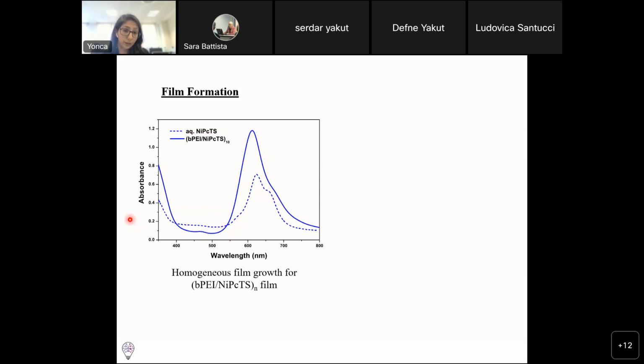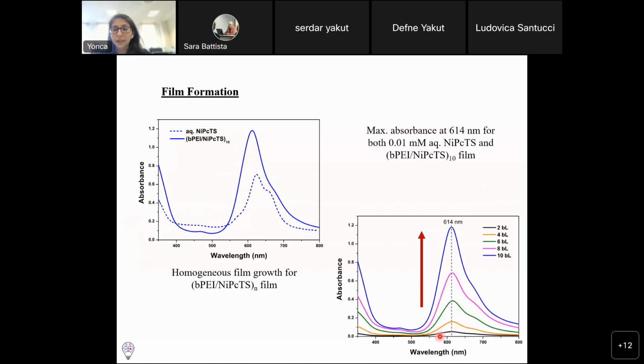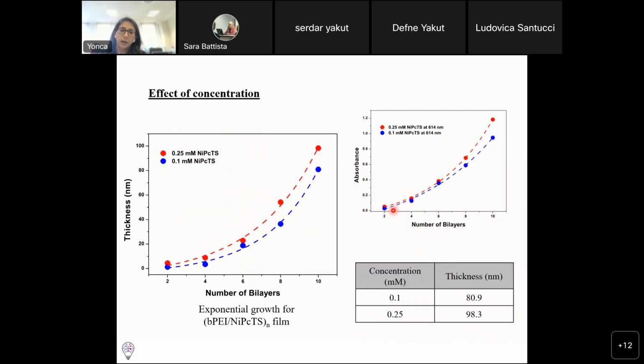Due to the advantage of the colored structure of phthalocyanine, we can actually do such a nice measurement. Thus, once you increase the number of layers, we are expecting to see an increase in the intensity, and this is the case. So as the number of layers increases from 2 to 10 bilayers, the black one represents the 2 bilayers of film, 4, 6, 8, and 10 bilayers. So at the maximum, you can see they are all growing linearly. Okay, growing linearly. Let's stop here because I need to show you how they grow actually. So, do they grow linearly?